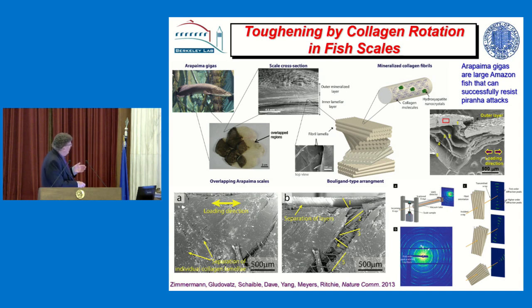But what's intriguing is when you put this in the synchrotron and do the small angle scattering, these layers of collagen will actually rotate to carry more of the load. It's a very interesting mechanism. It's seen in a lot of biological materials. But the collagen will basically rotate and carry more of the load. You can see it here. It starts off like this and it gradually rotates to carry the load. And this is a very, very effective mechanism of resisting fracture in the lower levels